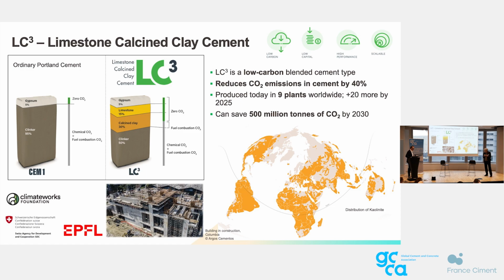This is a new cement, but the important thing is it's very much in the logic of what we've been doing already. For decades, we've been using things like fly ash and slag as substitutes. The issue already is we don't have that much slag and fly ash compared to the amount of cement we need. Slag, yes, you can put in very large amounts, like 70%, but on a worldwide basis, we only have 8% slag compared to cement production. So if you prescribe high slag in your product, you're just taking it out of somebody else's product, because nearly all that slag is already used.